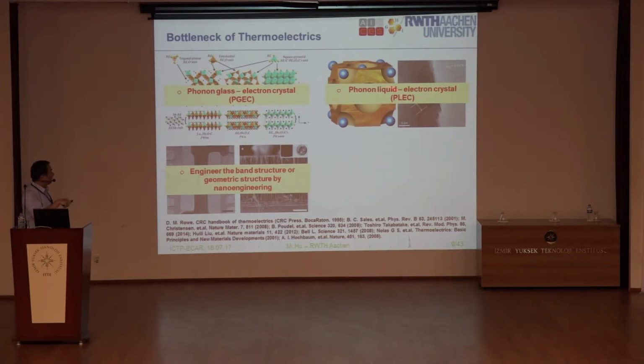And in recent years, people also proposed another concept called the phonon liquid electron crystal. Such an order-disorder structure is also semiconductor-like, so you can conduct the electrons very well, but in such a disordered or mixture structure, you can expect that the phonon transport can be very, very low. That's easy to understand, right? And then both methods can be combined with nano engineering. You can make some devices, bulk-like and then nano-sized, you can make a nanowire, a two-dimensional film, or polycrystalline and nanostructures, and then you can further reduce the thermal conductivity.